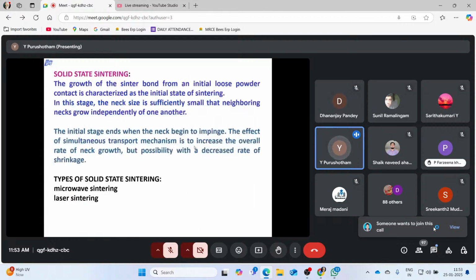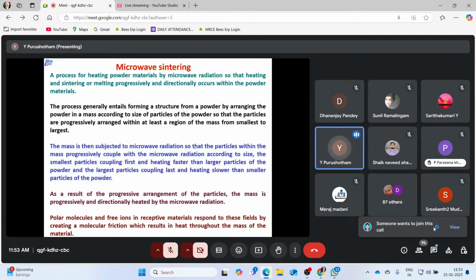Like this, different types of sintering are there. In solid state sintering, the growth of the sinter bond from an initial loose powder contact is characterized as the initial stage of sintering, and in this stage the neck size is sufficiently small that neighboring necks grow independently of one another. Solid state sintering includes microwave sintering and laser sintering. These are all different types. Microwave sintering is a process for heating powder materials by microwave radiation, so that heating and sintering or melting progressively and directionally occurs within the powder material.